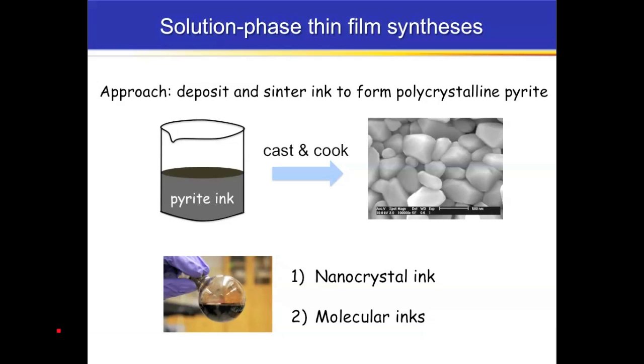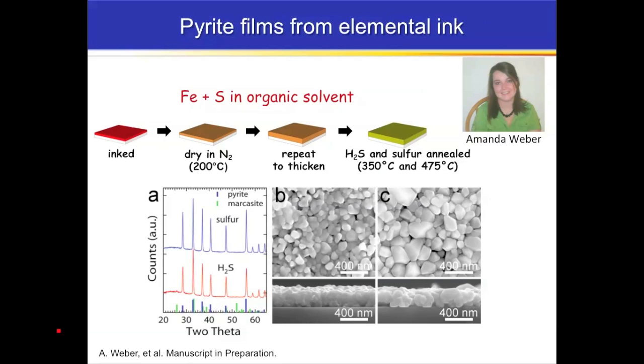Let me say something about what we do with the solution phase deposition. The idea behind solution deposition is to lower the costs in principle. We take a pyrite ink that could be a nanocrystal ink or a molecular ink. The idea is simple: deposit that onto the surface and then cook it in the presence of sulfur to get a polycrystalline pyrite layer. I'll show just very briefly two molecular ink approaches that we use.